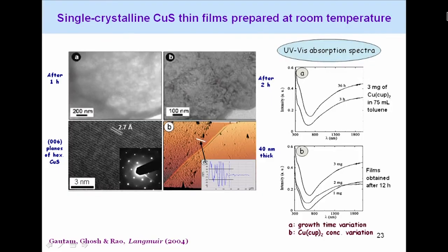In fact, I show this, don't worry about all the things in this picture, it is very busy. On the bottom left-hand side, you can see one picture of a sulfide with lines in it. That entire film across the interface is a single crystal. And you can see the black spots in the diffraction pattern. It's very difficult to make such films by ordinary physical methods. In physics, you do evaporation, you use all kinds of technology. You will not be able to make it. Here is a beautiful nanofilm, which is single crystalline at the interface. So a lot of this kind of work has been done in the last few years.